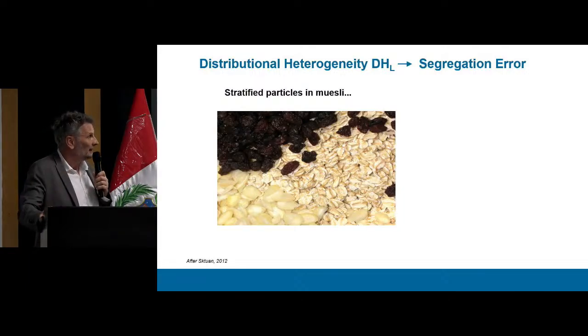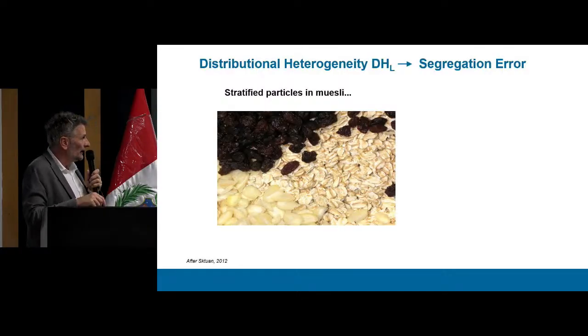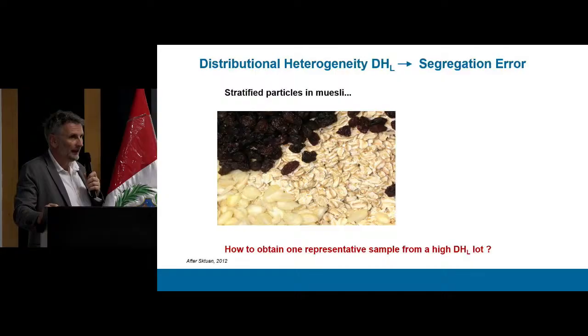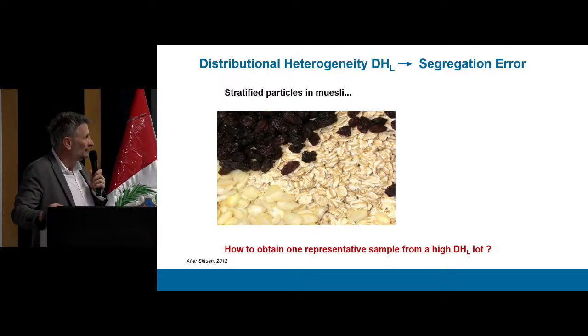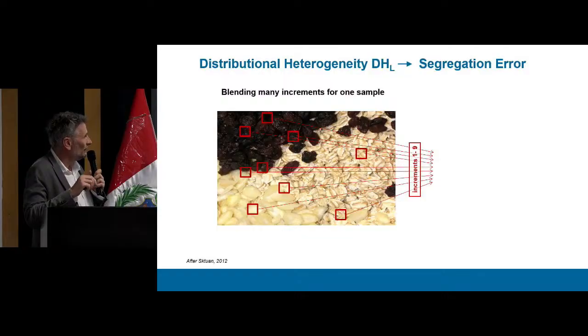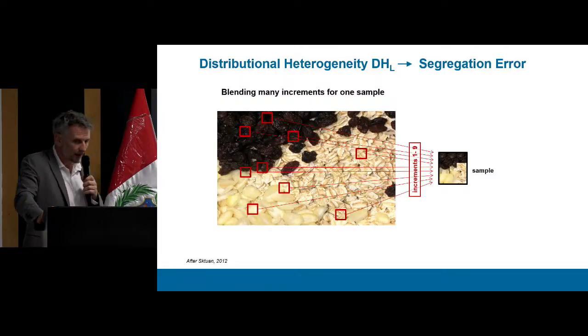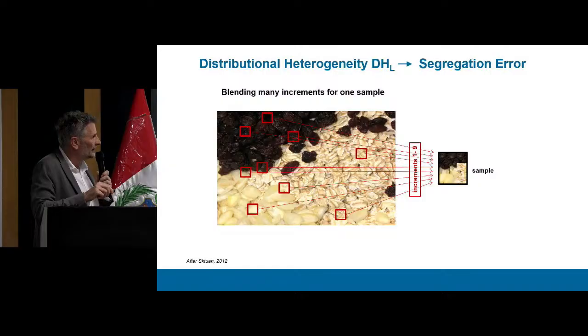That was the fundamental sampling error. Now we come to the distributional error or segregation error. Again, our muesli, and now it's not randomly distributed. We have some areas of high concentration of raisins and some areas where we don't have raisins in there. What we can do in that case, it's not recommended here to increase the sample size. What is more recommended here is that we take small increments, take smaller samples from different places of our lot, and finally produce one subsample, with subsamples taken from different sections in order to represent the whole lot.